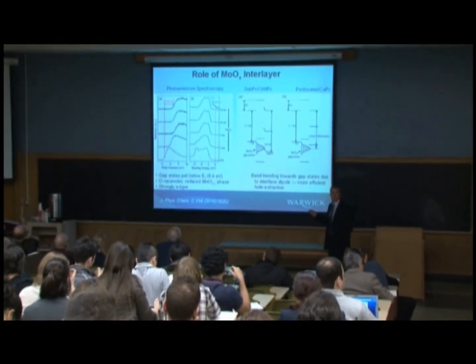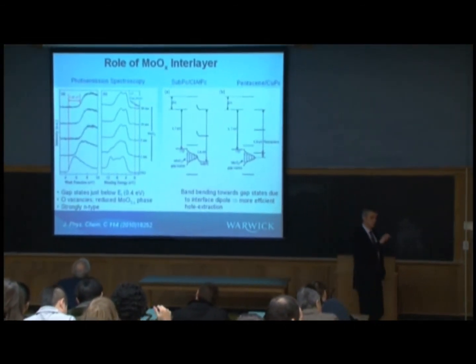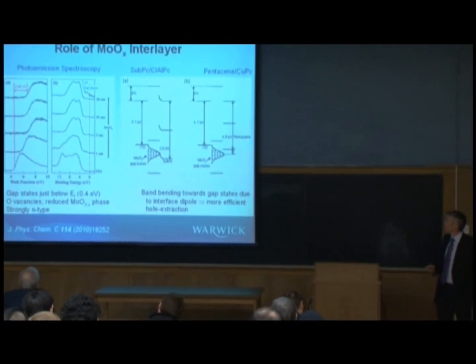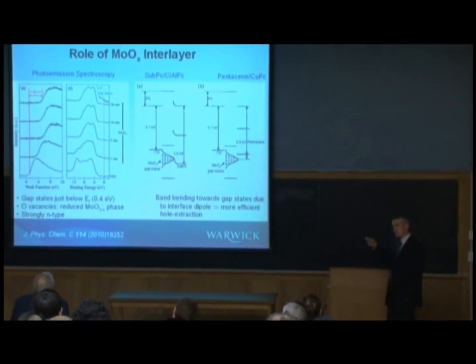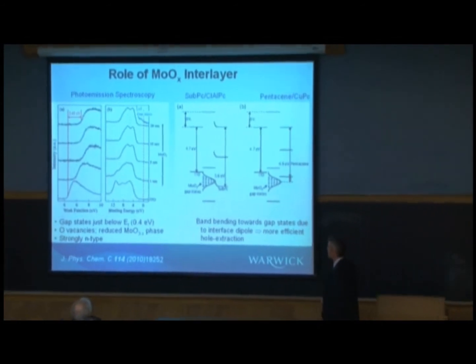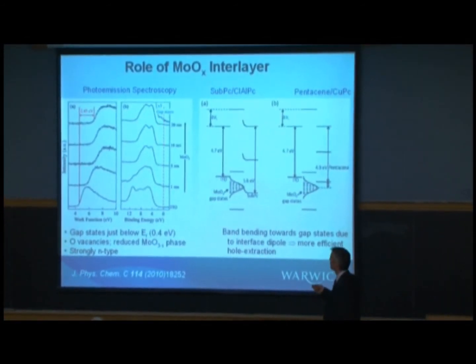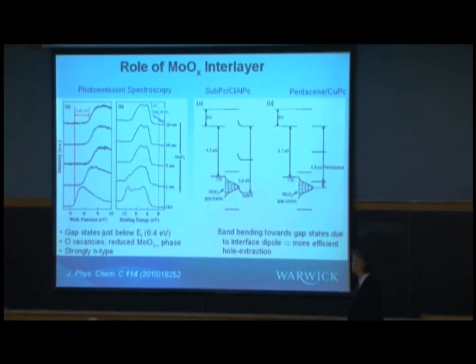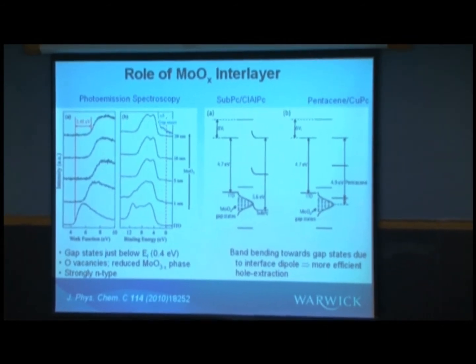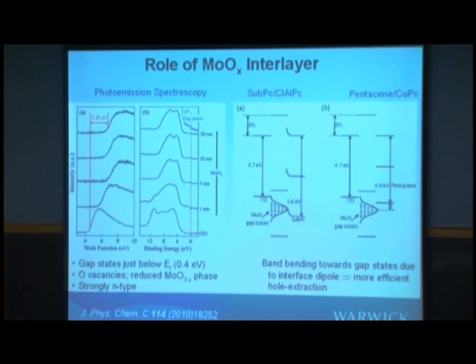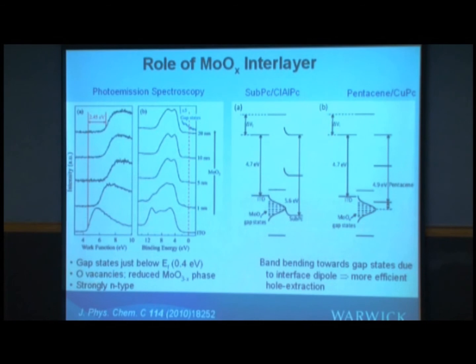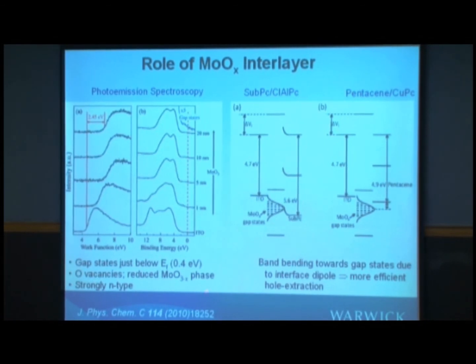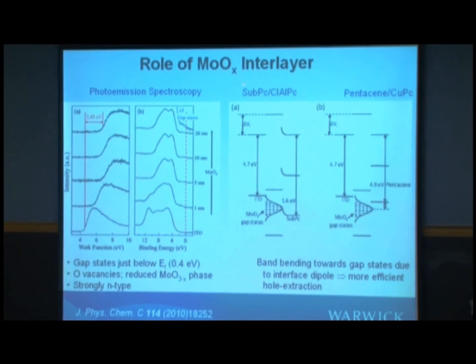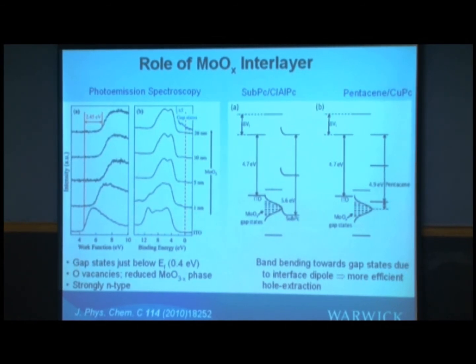And what you start to see are the appearance of these gap states just below the Fermi energy. And I'll show you some results for vanadium oxide which show a very similar trend. Gap states around 0.4 electron volts below the Fermi energy. And if you do analysis of the XPS data, the molybdenum oxide, there are oxygen vacancies, and it's a reduced molybdenum trioxide phase, which is why we tend to call it MoOx, because the stoichiometry is very variable.